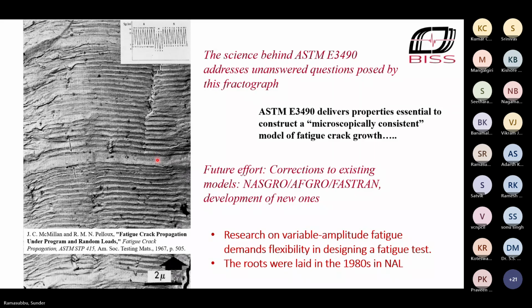Without going into the details, I can tell you that using the properties you get with ASTM E3490, you would be able to explain all these 3 interesting features you see on the fractogram. In other words, this property allows you to develop variable amplitude models of crack growth, which are microscopically consistent. And there are several papers that have been published in this regard, which show that with this property, you can model crack growth along with crack closure in a way that you can computer generate this fractograph and it'll match 1-to-1, at least qualitatively, with what you see here on this old picture.